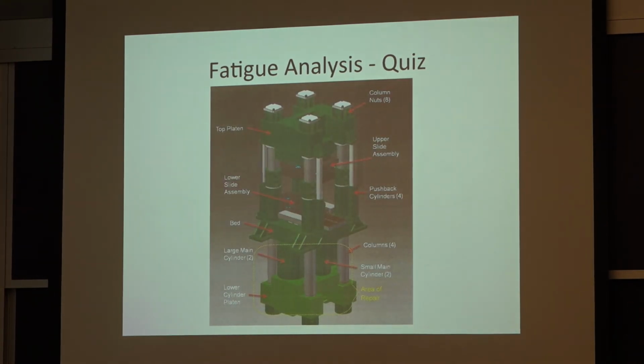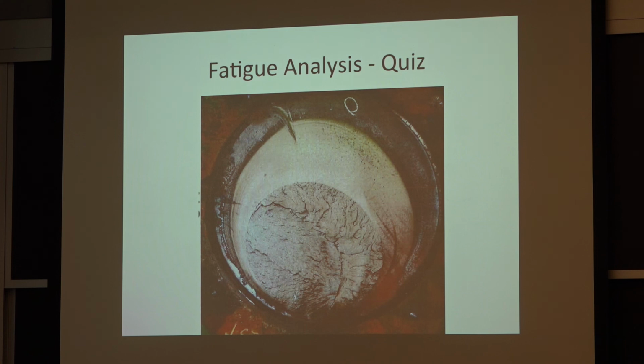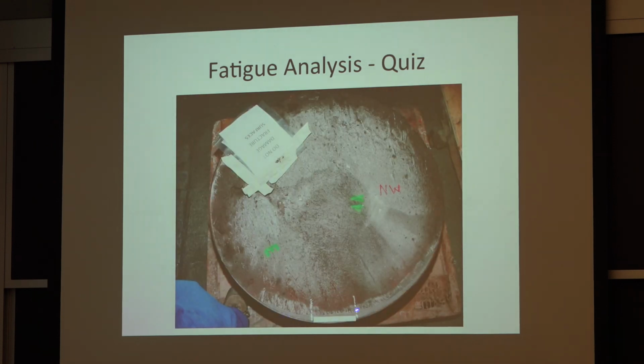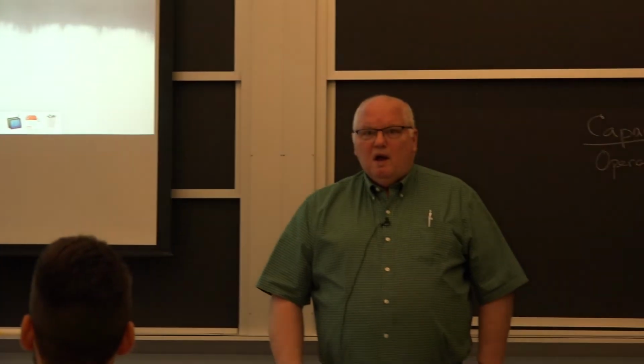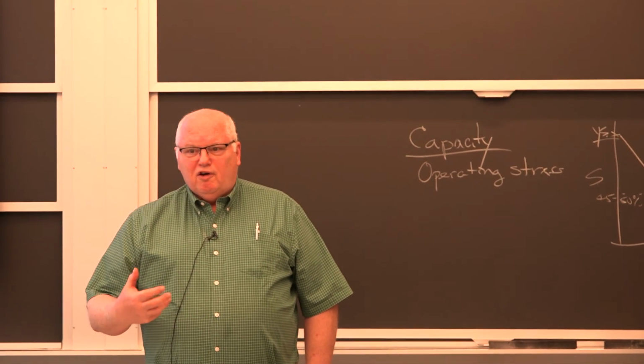I had another one with some really big bolts. This was a 50,000-ton forging press. There's only like half a dozen of these in the world. And the posts basically have bolts, 4 big bolts, about 1 meter across. Okay, so this one, stress concentration, there's the fatigue crack, there's the final fracture. They changed the steel, and they thought they were going to a higher strength steel and everything would be wonderful. Now it turns out the fatigue crack is this big. There's the final fracture area. Yeah, it was higher strength, but it still broke due to fracture mechanics, and we won't get into the fracture mechanics right now. But, okay, lots of things you can tell if you get into all the details.